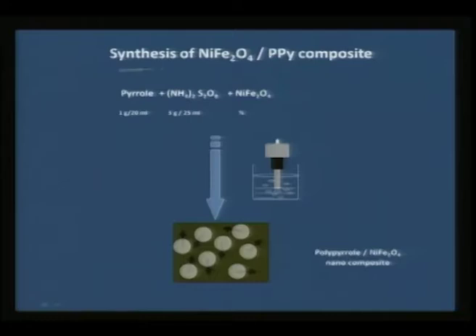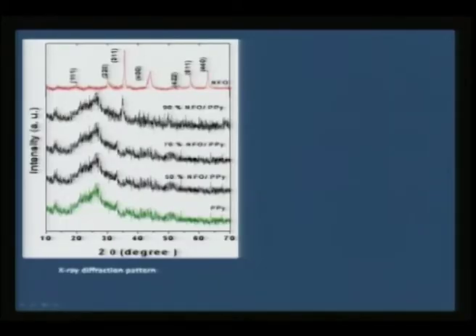Now, we can go one step further to prepare these composites, and as I already discussed with you, take pyrrole, then nickel ferrite, and try to in situ polymerize, then you can get this sort of composite, and this is the typical X-ray graph for the composite. As you would see here, PPY, which is the polypyrrole without any loading of nickel ferrite, and as you keep loading nickel ferrite even up to 90% of nickel ferrite in polypyrrole, you still see an amorphous pattern. That is the beauty. What does that mean? That there is an intricate mix of the pyrrole over every single particle of nickel ferrite.